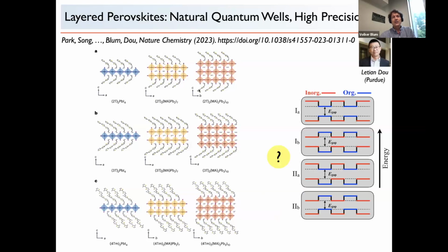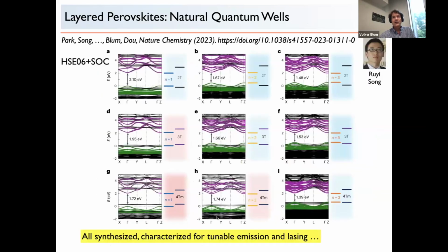We can do calculations. What we can do in short is we can find out what kind of quantum well this is. So will the electrons be on the organic component or will they be in the inorganic component? Same for holes. You can play this with 4 different combinations, but this really determines the optical properties of the materials. So we can calculate band structures in very short and find out these energy level alignments, and they agree with the emission properties, and Letian and others then went on and showed that this can also be used as lasing materials.